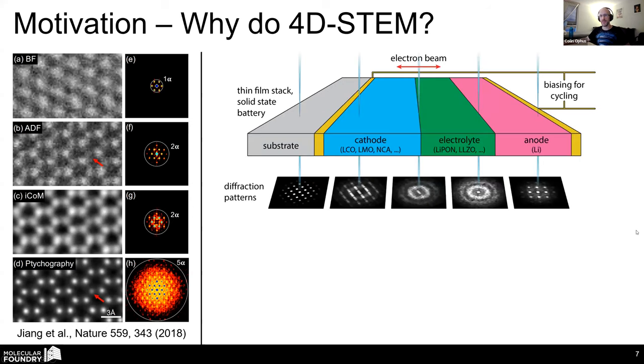The other extreme is ultra large fields of view. So what we want to do in the sketch I'm showing here, for example, of a solid state battery stack, is scan the entire 1 micrometer thick, 1,000 nanometer thick stack, and get diffraction patterns from all the different regions. Because these diffraction patterns come from essentially nanometer scale projected areas, they give you atomic scale information about the local material structure.